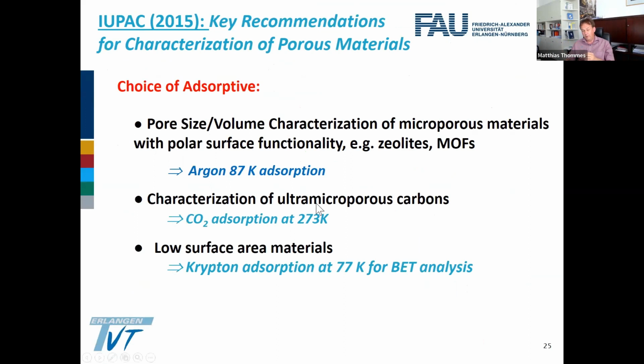Now, if you, however, have really highly tortuous, disordered ultramicroporous carbon, then even argon might be too big to get into the very, very tiny pores, or there might be diffusion restrictions. Even if it would fit into the pore network, in some of these active carbons it is so tortuous that it will take a long time for argon to adsorb in these pores. And then CO2 adsorption at 0 degrees is a key tool for doing this. And if you have low surface area materials, krypton adsorption is the standard methodology.